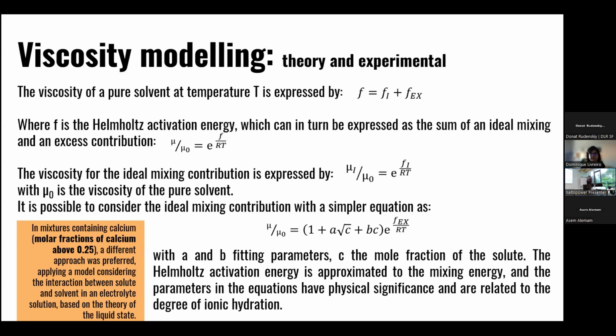And so we considered an interaction between the solute and the solvent in an electrolyte solution that is based on the theory of the liquid state. So here I reported only a few formulas, that is the approach that we followed. The viscosity of a pure solvent at a temperature can be expressed like this formula, that is the sum of an ideal mixing and an excess contribution.